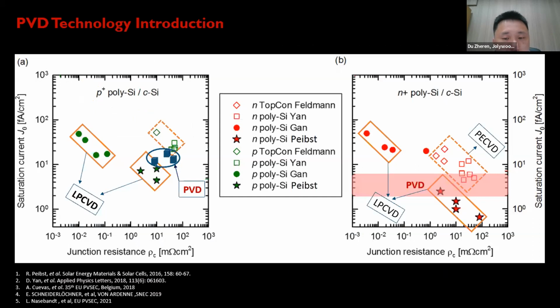So for TOPCon structure to achieve a very good selectivity, it needs to have a very low saturation current and also very low junction resistance at the same time. So the left graph actually shows the status of P-type doped polysilicon deposited by LPCVD, PVD, and PECVD. You can see from the graph that the saturation current and junction resistance are very comparable for all of these three technologies. So on the right, the graph shows the status of N-type doped polysilicon deposited by LPCVD, PVD, and PECVD. The saturation current for PVD technology is low, but the junction resistance range is pretty wide. This is also one of the challenges in the PVD process.